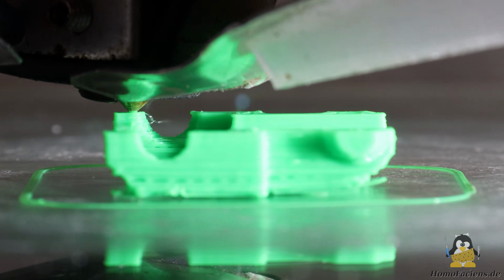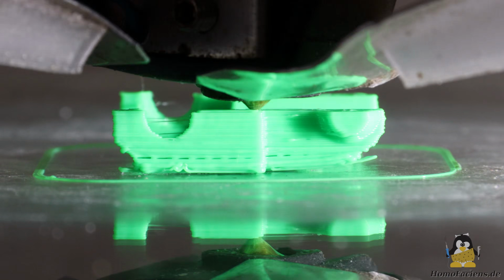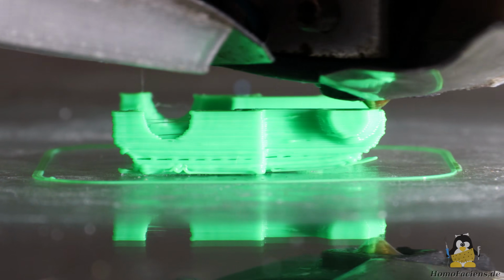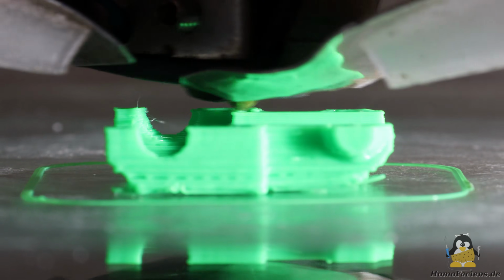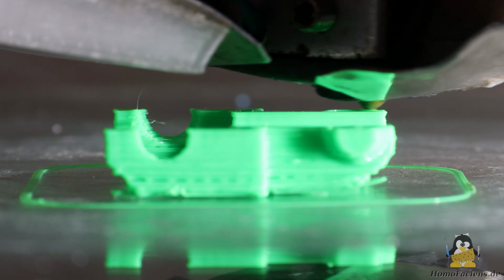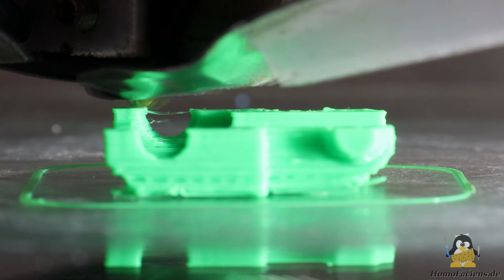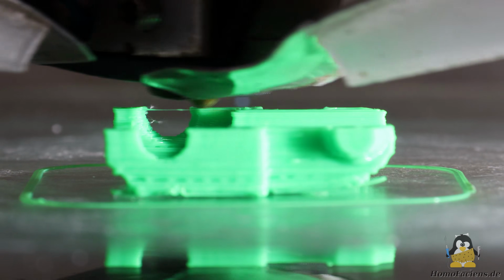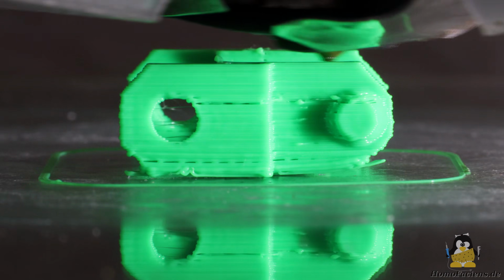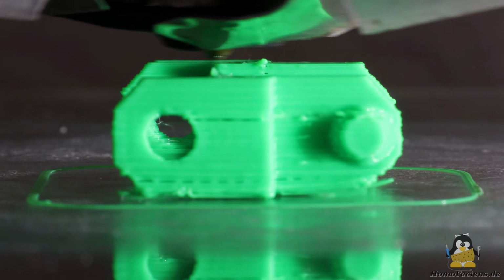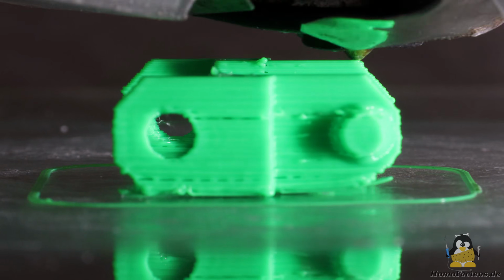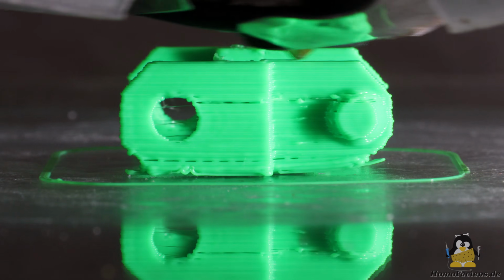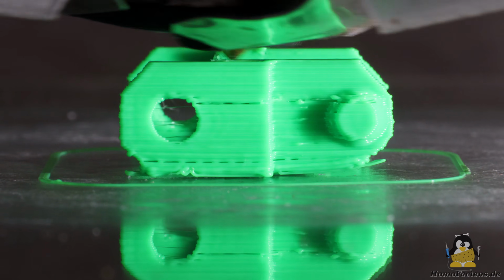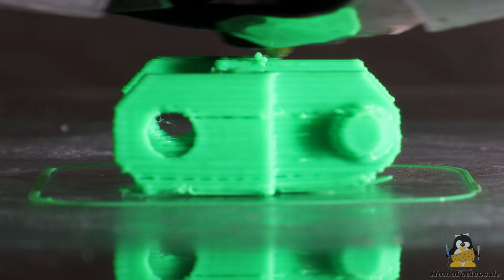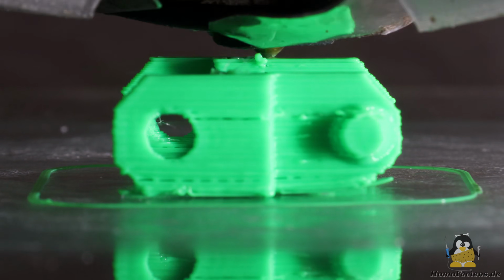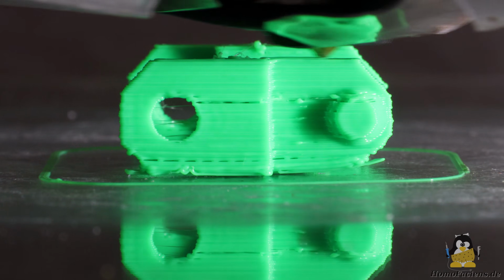Obviously the pellets are moved by the extruder with a very high degree of slippage. The smooth surface of the pellets, which ensures good flowability, causes the material to rotate along with the screw, as the extruder wall provides insufficient radial resistance to hold it in place. This also makes entering the extruder more difficult. Gaps visible on the walls of the track link indicate significant under-extrusion. In other areas, clearly protruding layers show that over-extrusion has occurred. I eventually addressed these pellet printing issues in a later video with a revised extruder design.